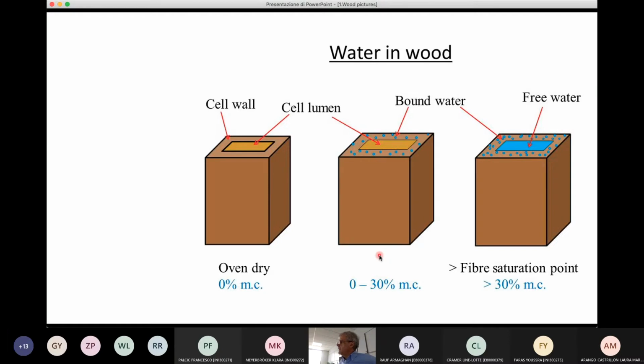When wood is alive inside the tree, the cell contains a lot of water: free water running inside the cells, and the bound water, which is the water bound with the polar attractions with the cellulose. When the tree is cut, all free water is quickly released from the cells, and what remains is only the bound water, which then establishes an equilibrium with the environment where the wood element is placed.